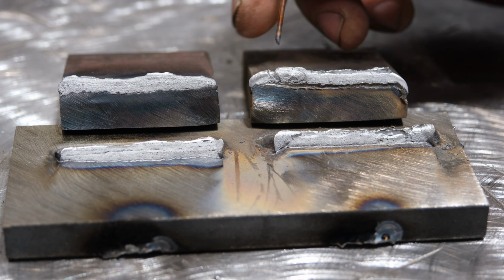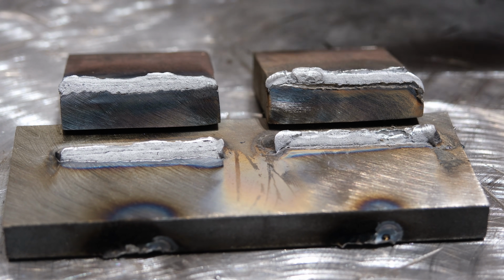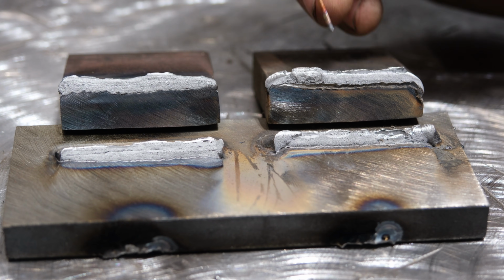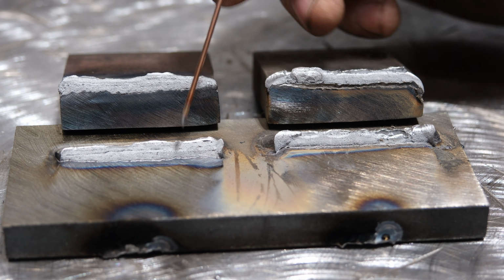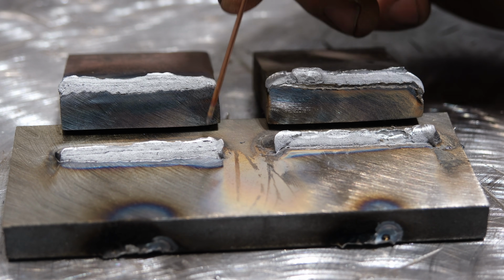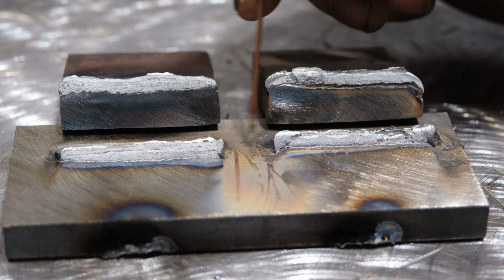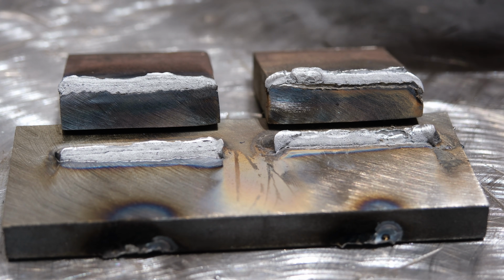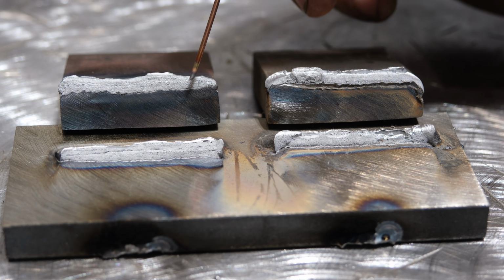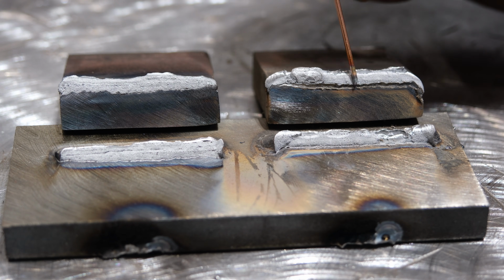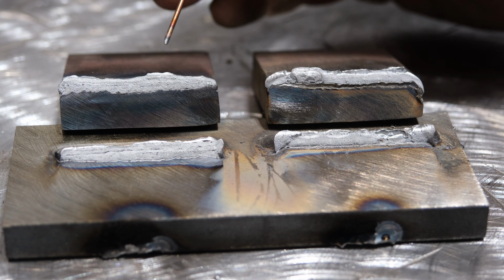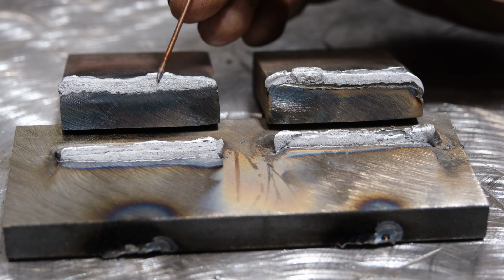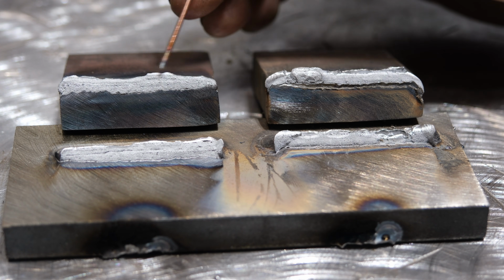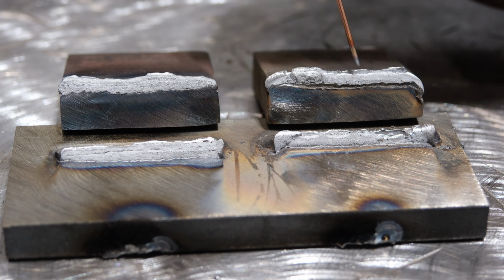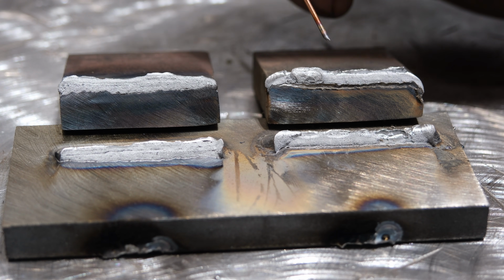So that's kind of a limitation of the wire processes, and again, you're still going to have a lack of fusion like this even with spray. Now beyond that, the heat input, undoubtedly, as far as BTUs put into this material, the TIG has to be higher because it took so many passes just to come close to equaling weld sizes. 3 passes of this, it's in the time frame, easily double, if not 3 times as long to do this TIG, 6, 7, 8 passes over this guy. So that is a huge savings.